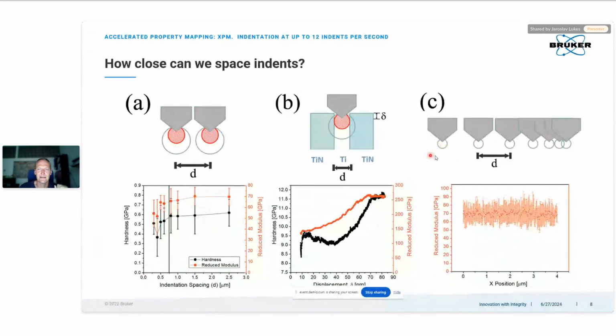And then ideally, if you're just interested in the elastic modulus, the spacing can actually be very, very small, because there is no plastic deformation left, so there is no deformation of the surface. There's supposed to be no change in the material properties after unloading, so you can actually space the indents very close to each other, so you get a flat line for the reduced modulus over the lateral positions here. So elastic modulus is actually more forgiving, if you're interested in the elastic modulus only, but hardness is a very different story, because you have to take into account the plastic deformation zone under the indenter.